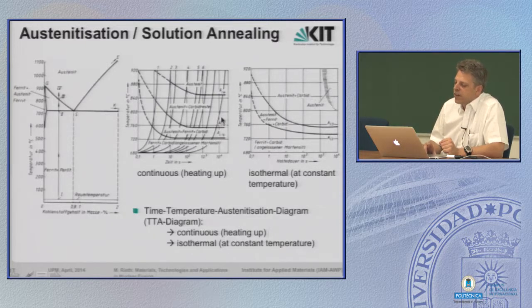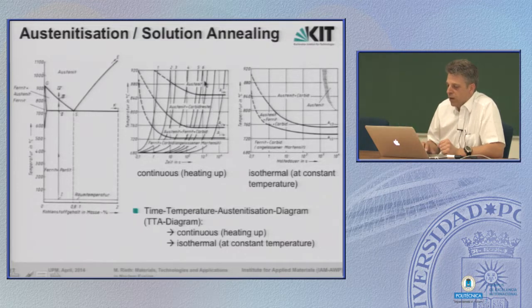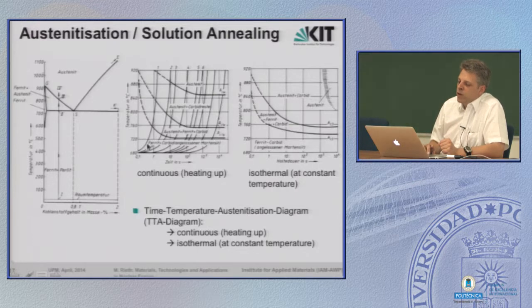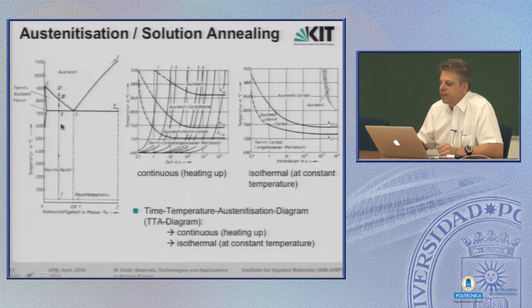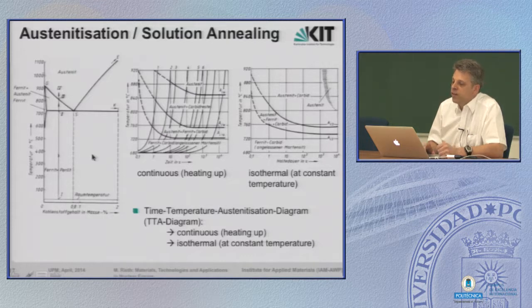If you do this very slowly, then everything goes according to the phase diagram. At some temperature, the ferrite and carbide dissolve. Then at higher temperature, you reach a phase where we have austenite, but still some carbides which are left over. And only if you go to even higher temperature, when you are here in the middle of this phase, more or less, and wait some time, then we have 100% austenite. If you do it too quickly, or rather fast, then all this dissolution cannot take place, and what you end up with is not a complete austenite, but there are still pearlite phases or carbide phases inside.